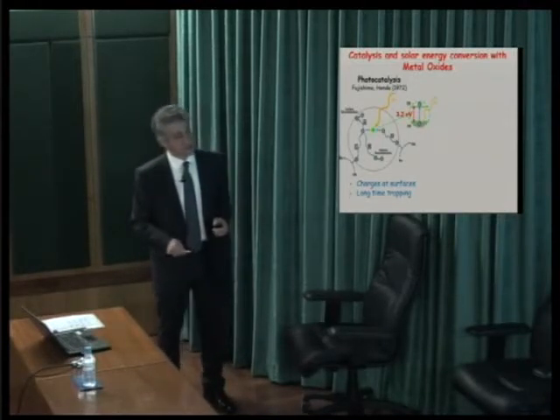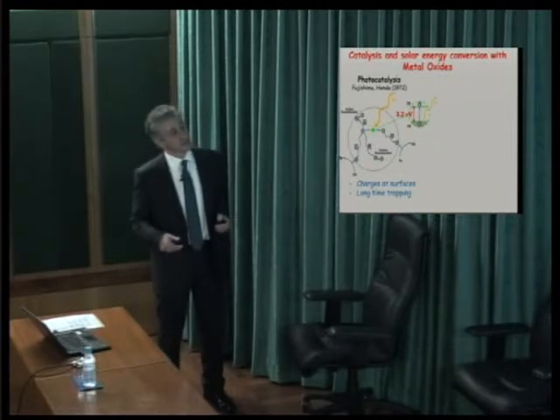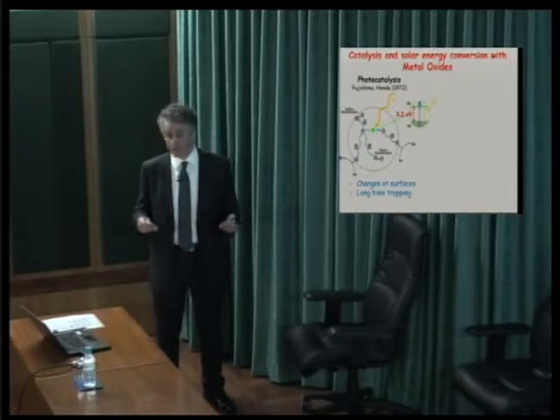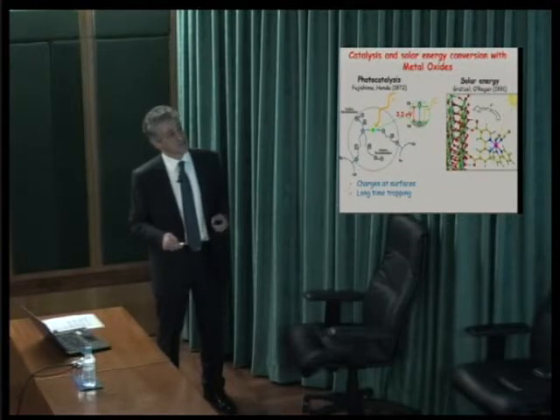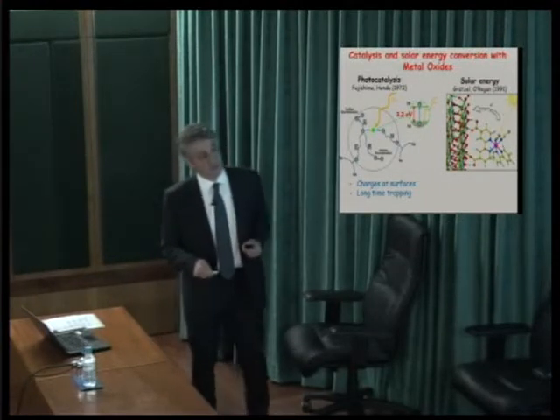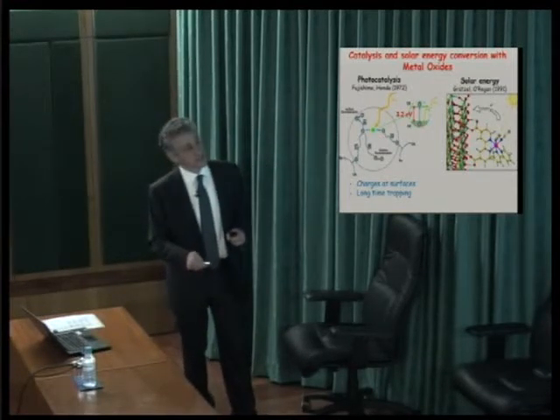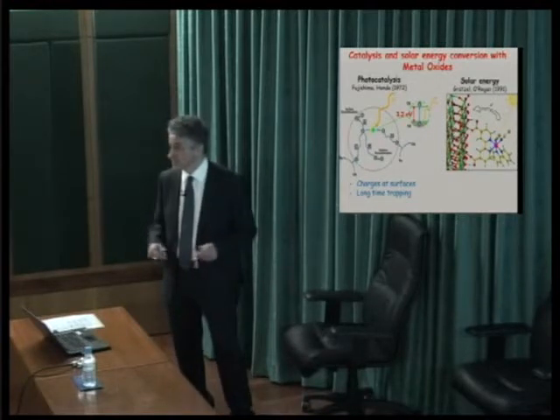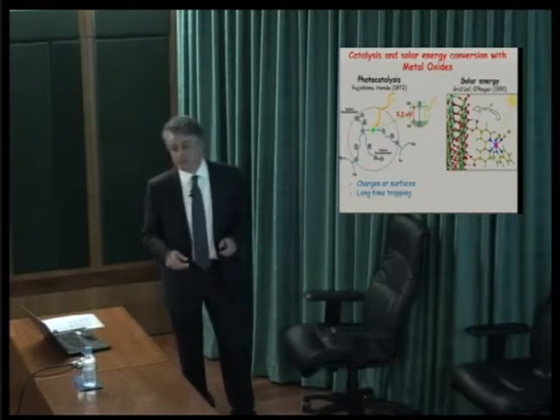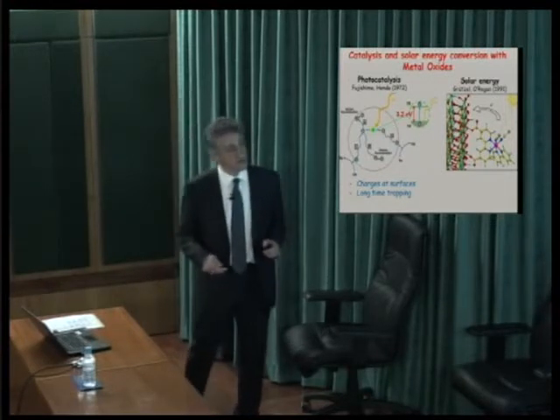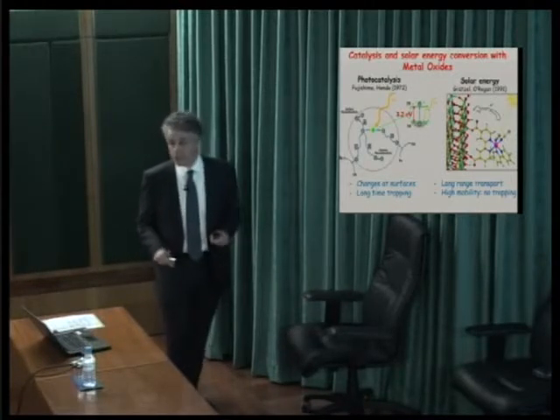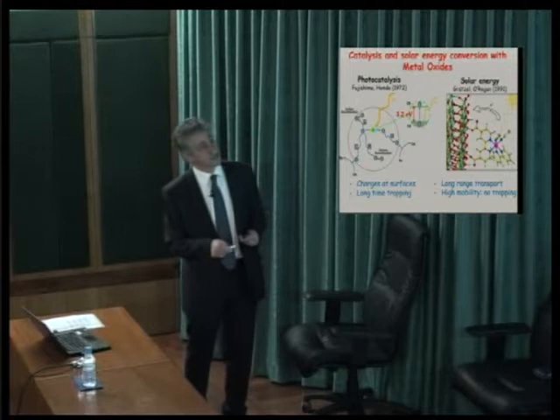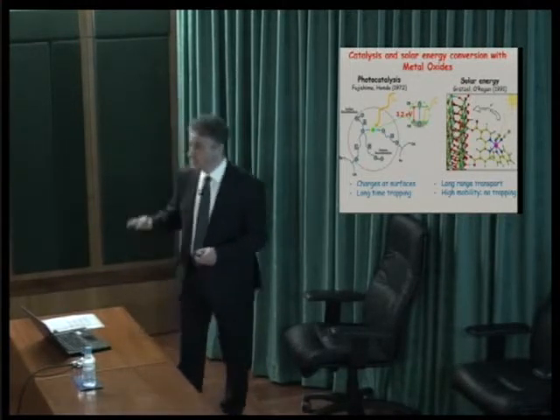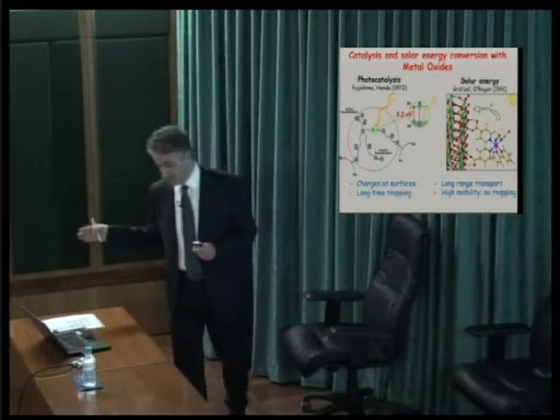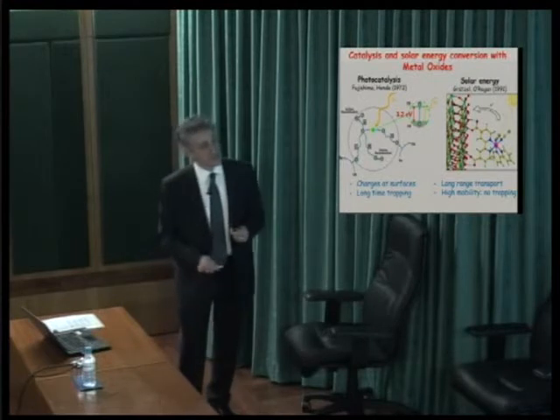For this process, you want charges at the surface and you want them to be trapped for a long time. Whereas the problem in this application is that the gap in these materials is too large for the solar spectrum. And therefore, my colleague at the EPFL, Michael Gratzel, had the idea of anchoring antenna molecules, which are ruthenium complexes, that capture the light and inject an electron, and then if you put a difference potential, you can get current. And this is the basis of the dye-sensitized solar cells, which are also called Gratzel cells, for photovoltaics. And the requirement in this case is you want long-range transport and high mobility, so these applications are quite opposing each other.